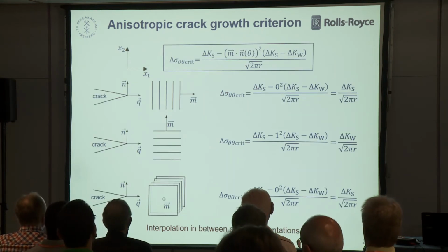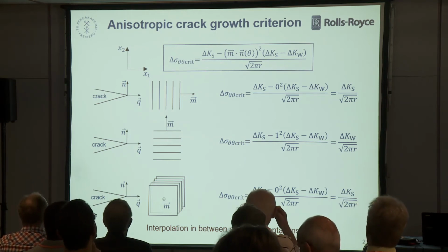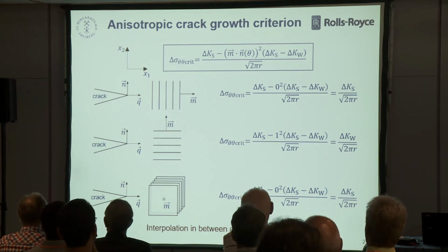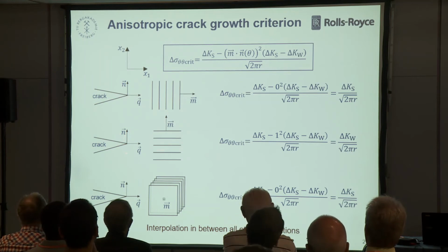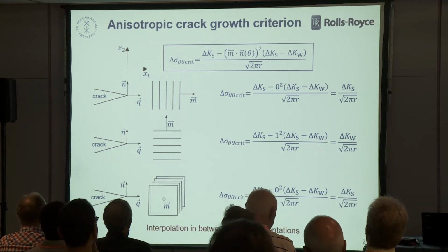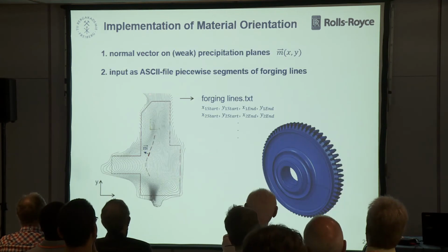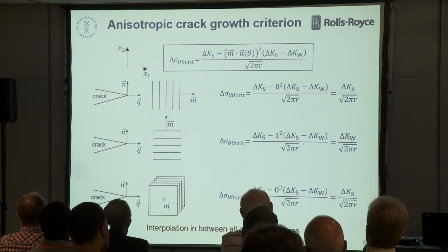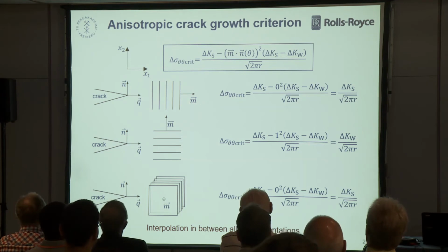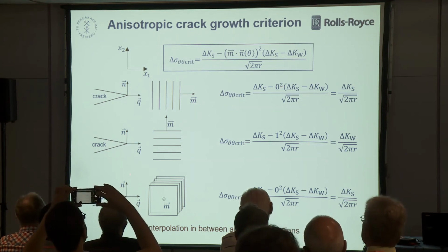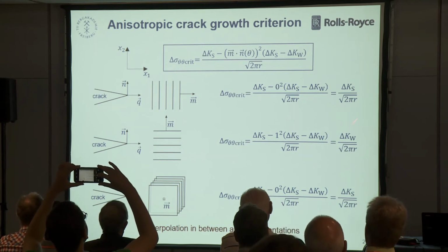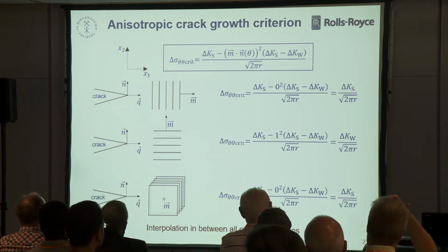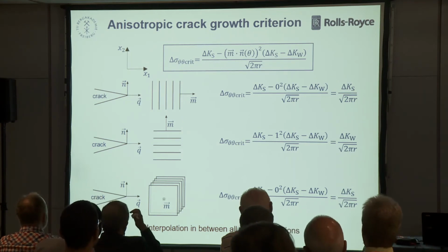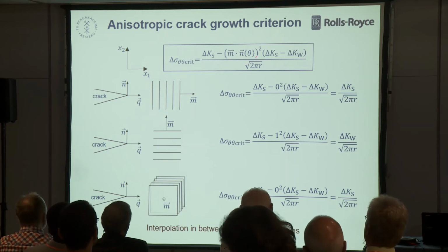This is this formula. If we consider the simple cases, let's start here, where the crack goes parallel to the precipitates. So m and n have the same direction. The scalar product is 1, and we arrive at the critical stress being exactly this value for the weak direction. Contrary, if we have the other two directions where n and m are orthogonal to each other, then the scalar product is 0. Or here it's orthogonal, but out of plane. It's also 0. So we arrive at the strong value. But important is that in between, for all other directions, this function interpolates.